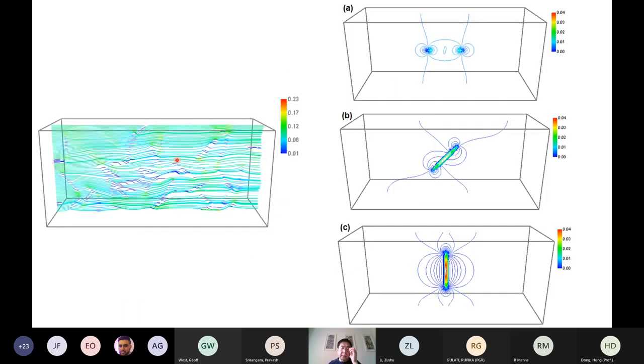So the visualization is quite important, because we don't know, if they have an inclusion there, what the temperature difference will be. People try to answer this question: if I have an inclusion, is the temperature inside the inclusion higher or lower than in the matrix? This calculation and visualization can actually tell you. If the inclusion is parallel to the electric field, the temperature inside the inclusion is lower than the matrix because there is no or very little electric current passing through it. However, if you rotate it, you see gradually the temperature inside the inclusion increases. If it's perpendicular, the temperature inside will be much higher.